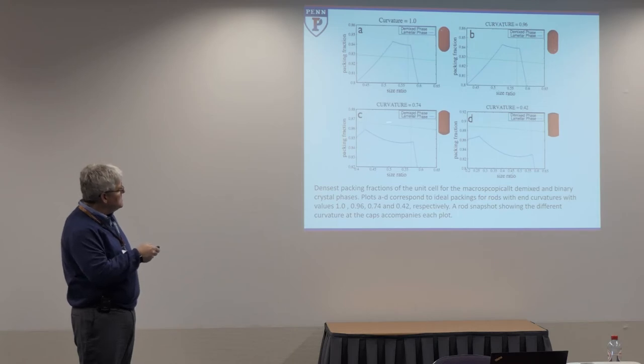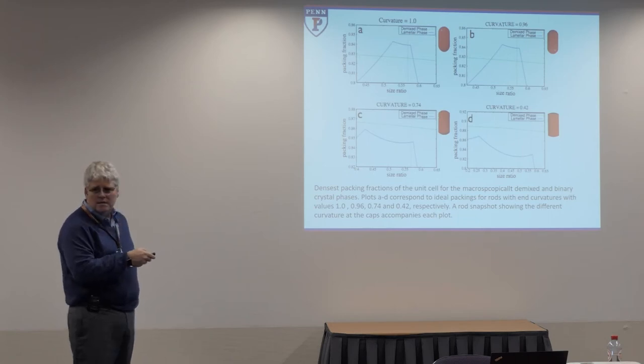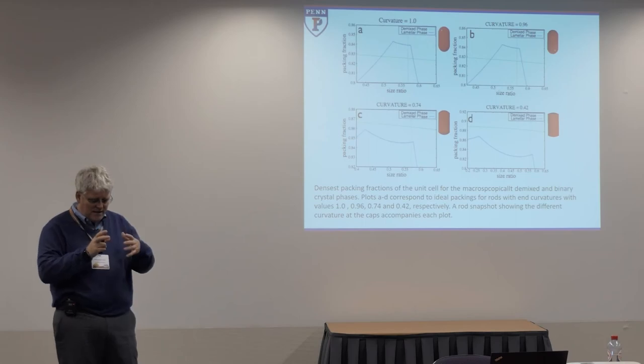So in this particular case, one of the pieces that is most important is the curvature at the end of the rods. When the rods are the right shape at the end, they pack very efficiently along the sidewalls and have a very strong entropic driving force. But at the ends, there's this extra free volume because the curved ends can't fit together efficiently. And so that leaves a little space for another material to be able to intercalate into the system.